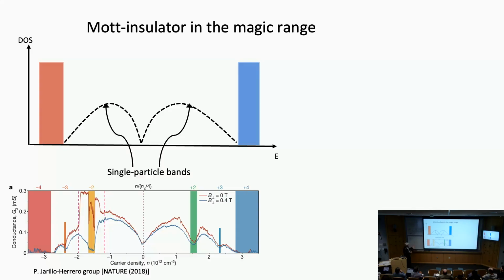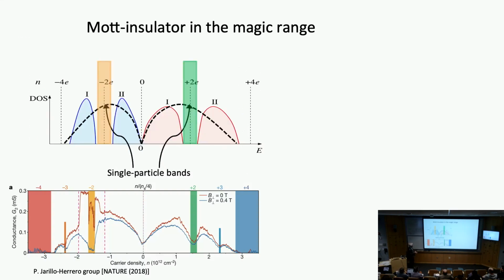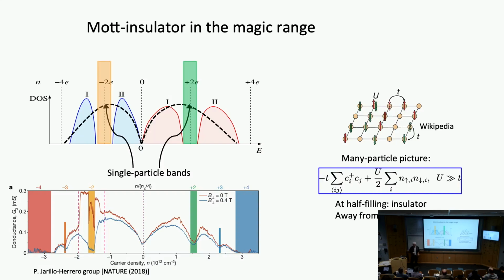But still, this theory is a long way from what is actually seen in experiment, because in experiment you have all this extra structure in the density of states. So basically we would like to be able to produce something like this. Go from the single particle bands that come from the DFT type of calculation to something that involves sub-bands. I labeled them 1 and 2. These are basically sub-bands on the hole side and on the electron side to capture what is going on in the experiment. But as I already mentioned, you can't do that at the level of density functional theory. You have to invoke a very different type of picture.